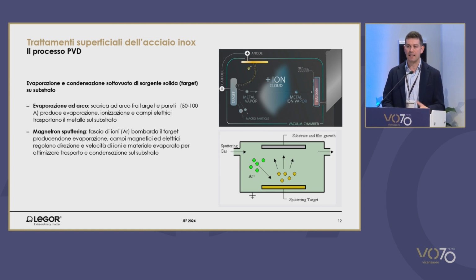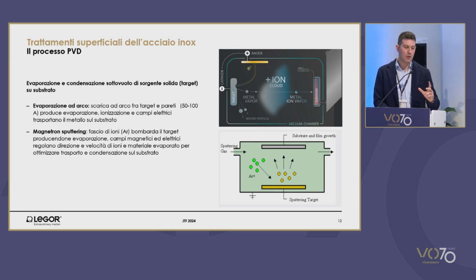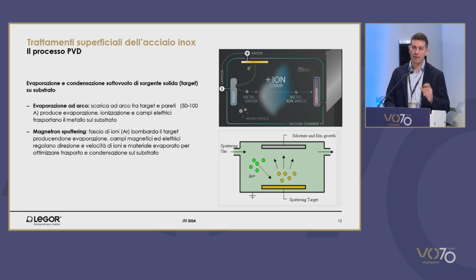PVD stands for physical vapor deposition. It includes the evaporation and condensation of a solid source, which is often defined as target. There are many techniques that can be used for PVD, depending on the type of metal being evaporated. In jewelry, usually it resorts to arc evaporation. An arc discharge is triggered between the target and the walls of the deposition chamber. Discharge with a current of the order of some 50-100 ampere is localized over a limited region of the target surface. There's also sputtering that can be used.